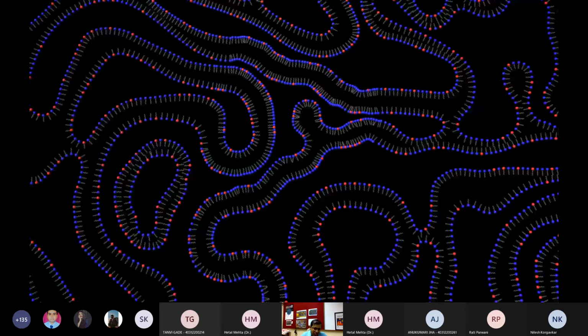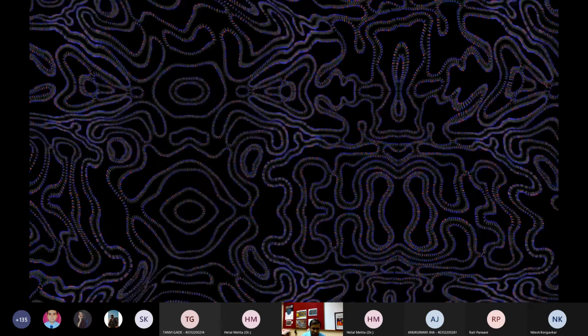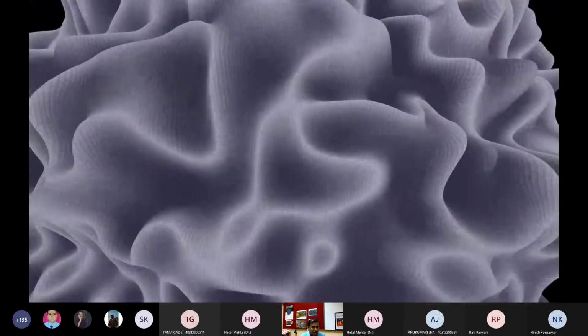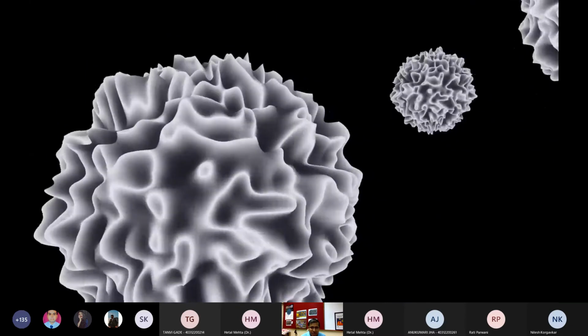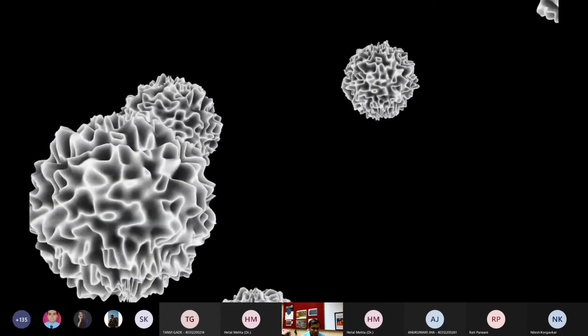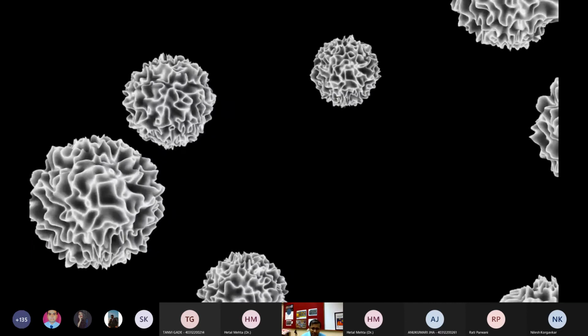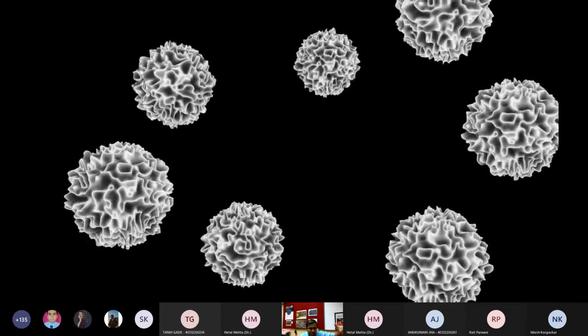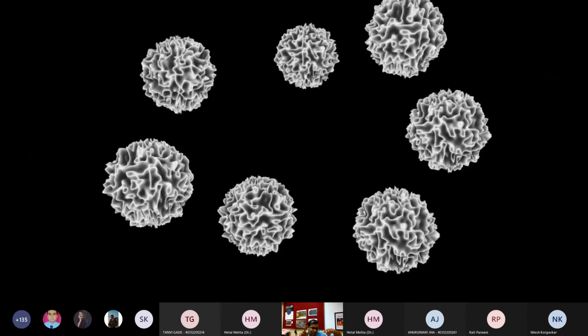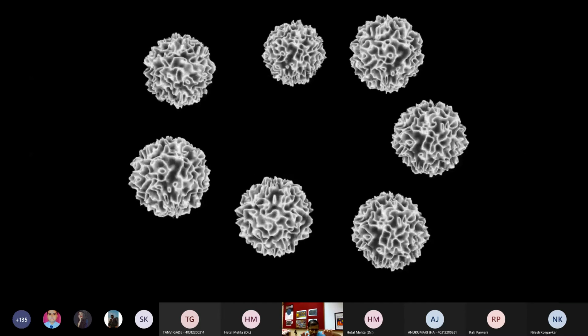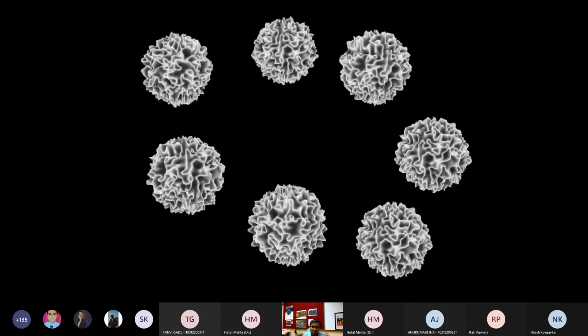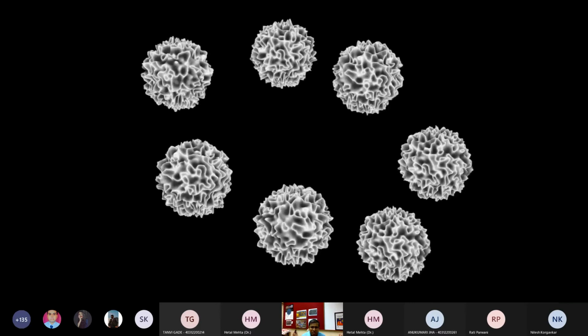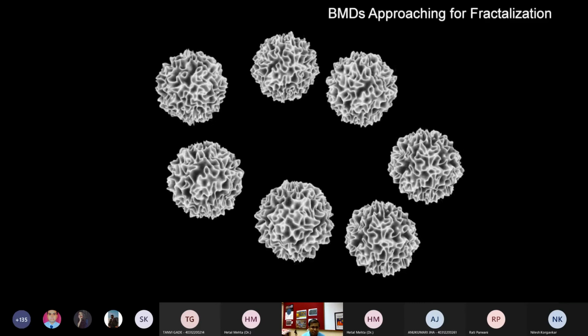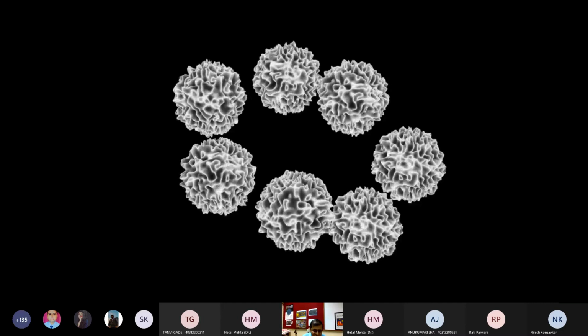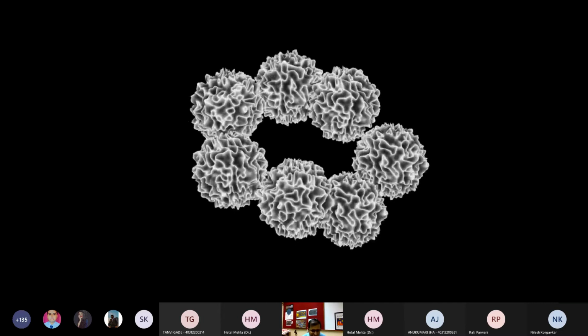And then we realized that these are not floating flat in the solvent, but they are in the form of a droplet. We call them bicontinuous microemulsion droplets, because it is a microemulsion, with cyclohexane or xylene and water, two phases continuously mixing. So bicontinuous, and these are the droplets. And these droplets are not the nanoparticles. Actually, these are droplets made up of water, CTAB, and xylene. And these are like a reactor. And in the channels that you see, we can grow the silica. So by tuning the size of these droplets, I can tune the size of the nanoparticle. We can keep them away, you get smaller particles, or we can force some of them to merge and increase the droplet size. And if you get bigger droplets, you will be able to get bigger silica nanoparticles. So that's how we were able to tune the sizes as well as the other things like morphology.